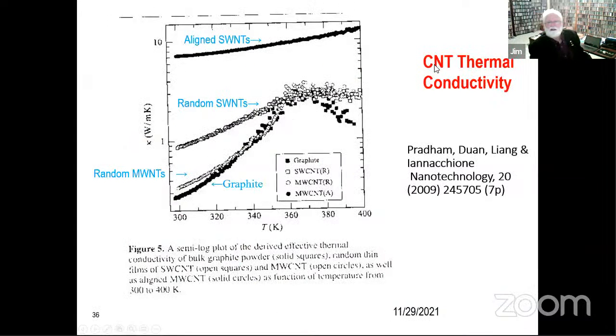So carbon nanotubes also possibly will present a solution to the thermal issues, thermal cooling of chips that I mentioned before. Here's the thermal coefficient of conduction for graphite. Remember, graphite is basically lots of layers of graphene, random mixtures of multi-wall nanotubes. This is what people currently use graphite for, cooling.